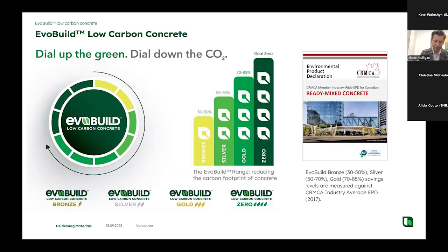which was built by essentially taking a survey of a statistically representative number of concrete plants throughout Canada, figuring out what a typical concrete mix looks like for 20 MPa, 25 MPa, 30 MPa, etc., assigning carbon intensities for all the different constituents that make up that mix, and figuring out what an average carbon intensity is for 35 MPa, 45 MPa, etc. concrete. Our EvoBuild structure looks at those carbon intensities on average, and essentially, if we're able to